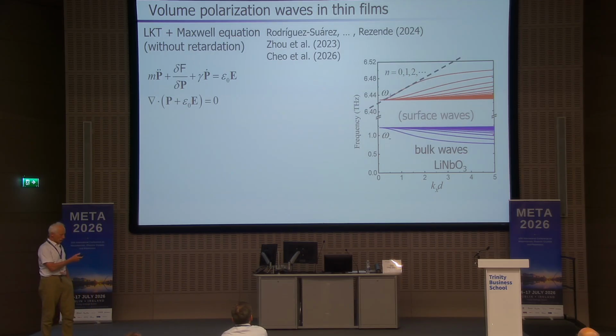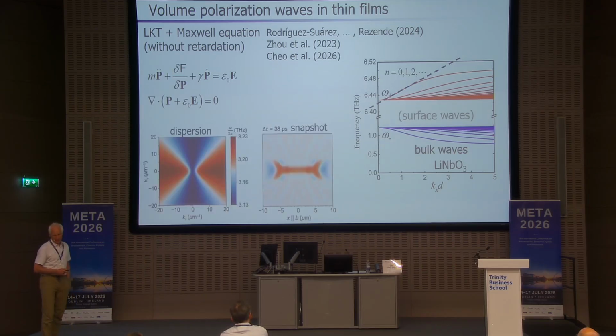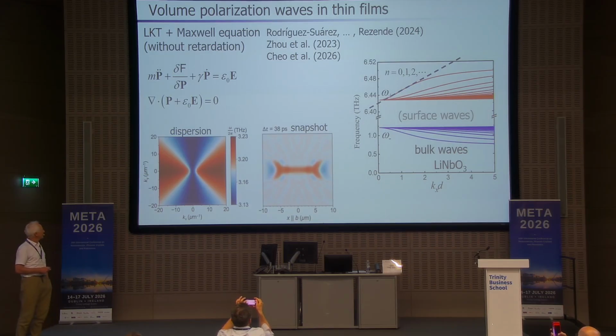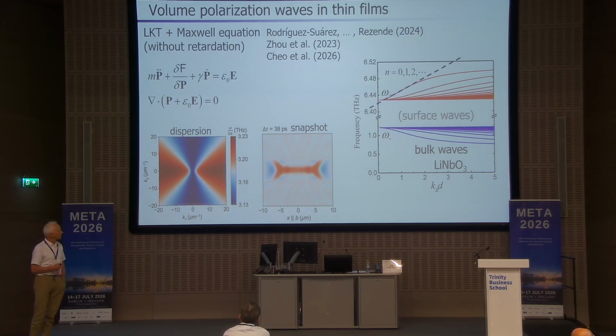Now, this mode, you can then plot it in a two-dimensional way. This has been done by Cheo et al. On the left side, you see the dispersion. On the right side, you see the temporal response, a snapshot after a few picoseconds, which looks very similar to what we see in the experiments. So basically, we can explain this acceleration of the signal in terms of dipole-dipole interactions, electrodynamic interactions.